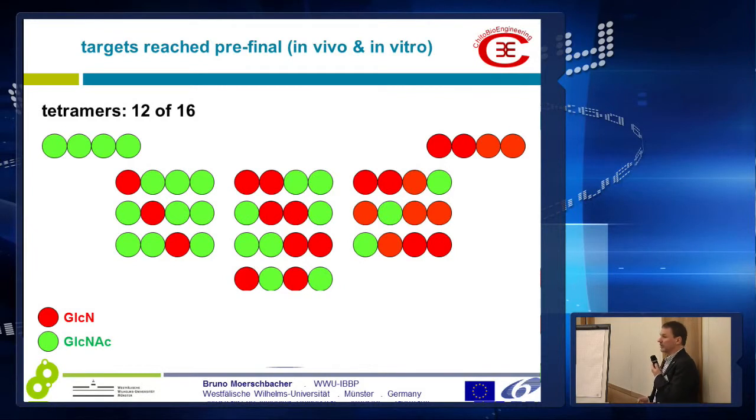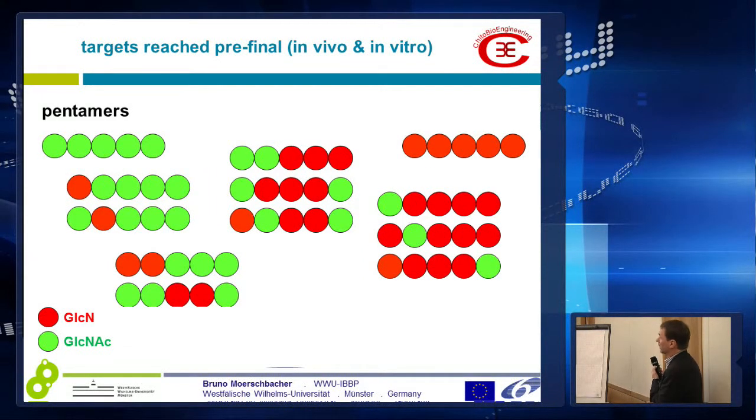So a few challenges remain, but the diversity has dramatically increased compared to what was available at the beginning of the project. Also, we have a selection of different pentamers, and in principle, we can also generate the hexamers. The problem there is that in vivo, hexamer production is still very low, most likely because of the insolubility of the fully acetylated chitin oligomers. At DP6, they are still soluble to some extent, but if they grew larger, they could become insoluble. And we guess that the DP6 already is too insoluble to be produced in vivo in good quantities.